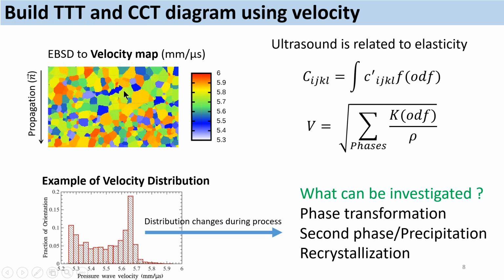So a microstructure in metals is composed of grains. We all know that. Those grains have a crystallographic structure, and often in metals, those crystals are oriented in different directions. This is what I have represented here in this map, in which the color corresponds to the speed of sound for a wave which propagates vertically in the sample. So you can see that there is a broad range of speed of sound for each grain.